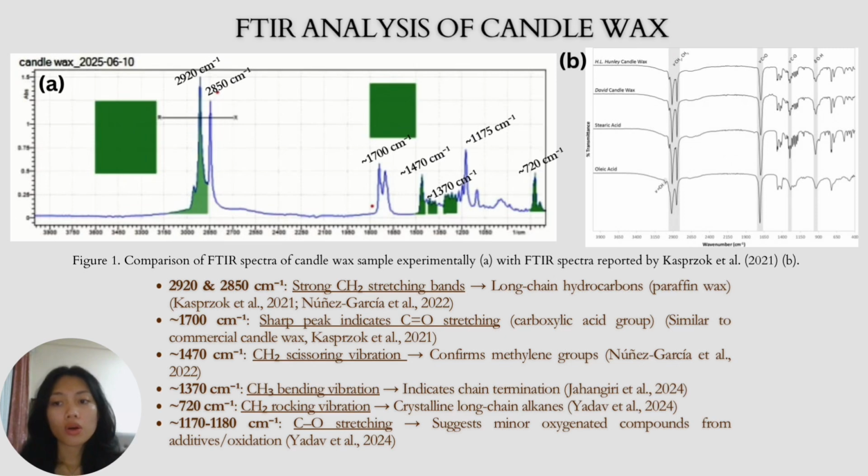So, as a conclusion, overall, this result confirms that the candle wax is primarily paraffin-based, but not entirely pure. It likely contains small amounts of additives or oxidized products, which is common in commercially formulated candles.